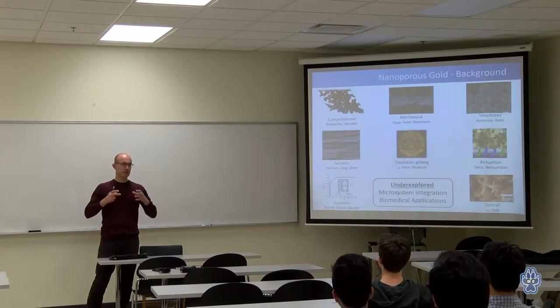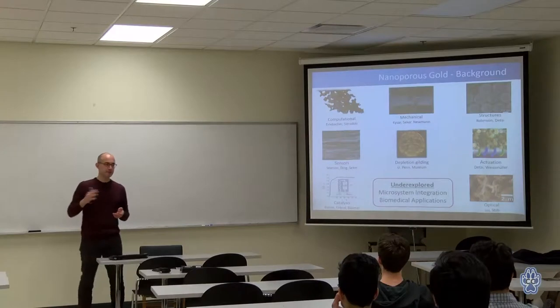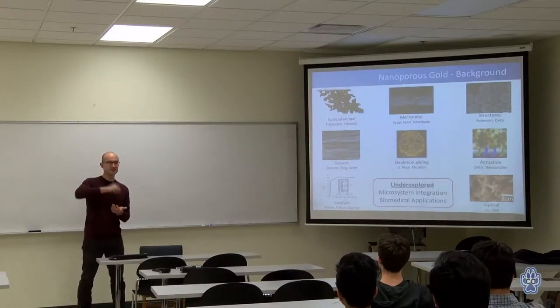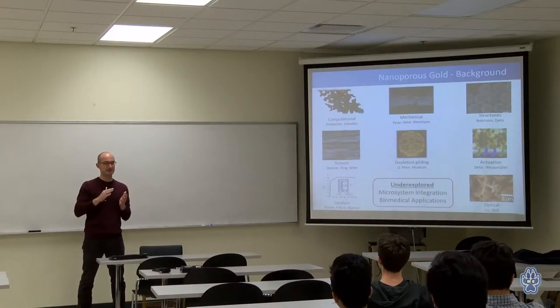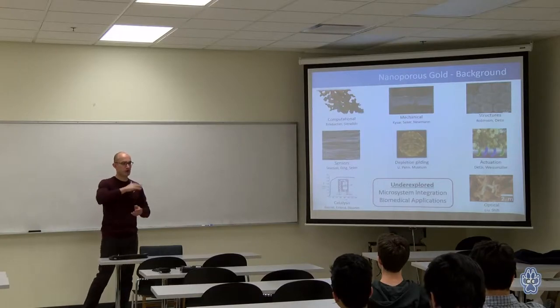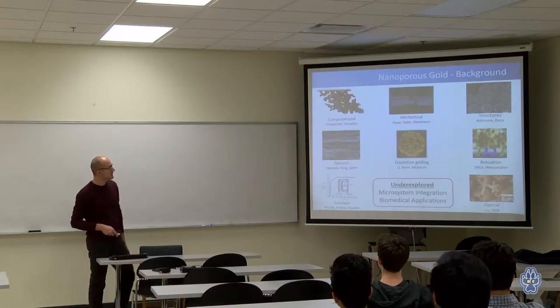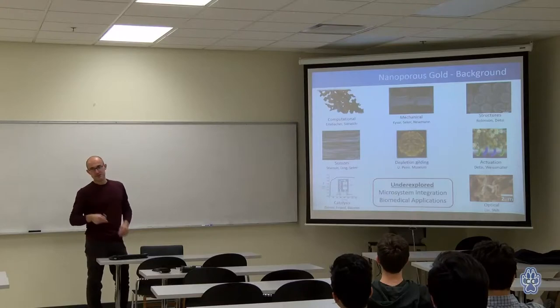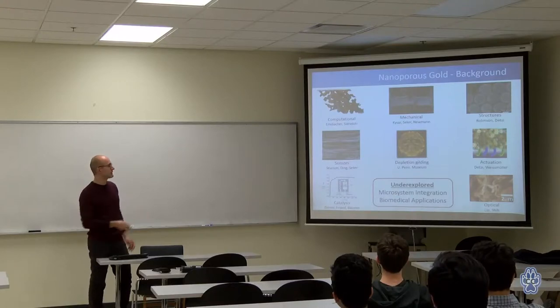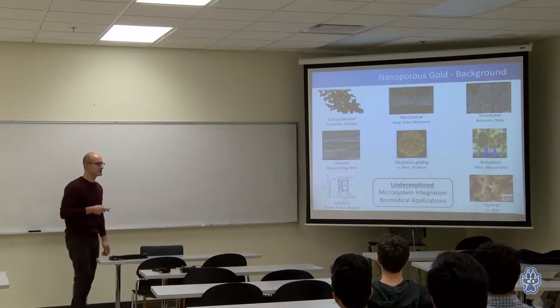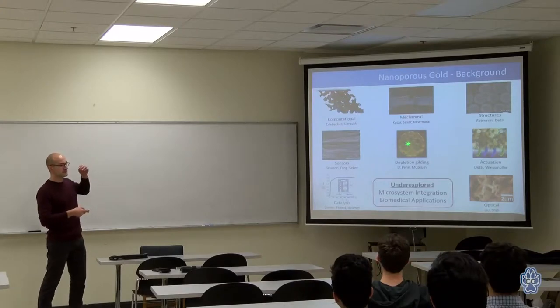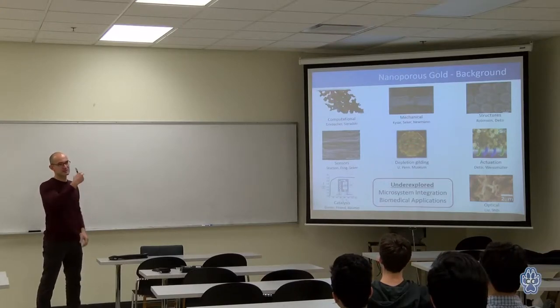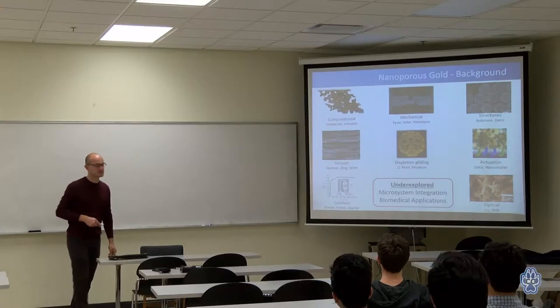And copper and gold is mechanically very sturdy, but it does not have that gold shiny finish. So goldsmiths back in the day leached the copper out of the surface and compacted it to make gold on the top surface, so it has the shiny finish. But as you can imagine, access to scanning electron microscopes during pre-Columbian times was not very easy. If they had looked at it at that time, they would have actually seen the same porous morphologies that we see there.